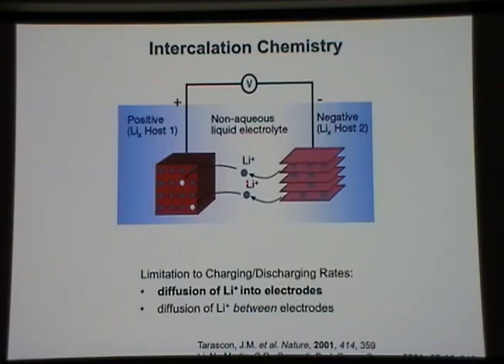That's exactly right. There are changes in bond lengths — as you change from iron 2+ to iron 3+, say for lithium iron phosphate, or cobalt 4+ to cobalt 3+, there are changes in bond lengths. You're also adding lithium ions which take up a certain volume, so the entire electrode has to expand. When you charge this battery and force lithium over to the graphite side, this electrode is going to shrink and the other expands — you get this expansion and contraction. If you've ever noticed that your cell phone battery stops keeping a good charge, what has most likely happened is your electrodes have pulverized themselves and they're not in good electrical contact to the metal foil current collector anymore.